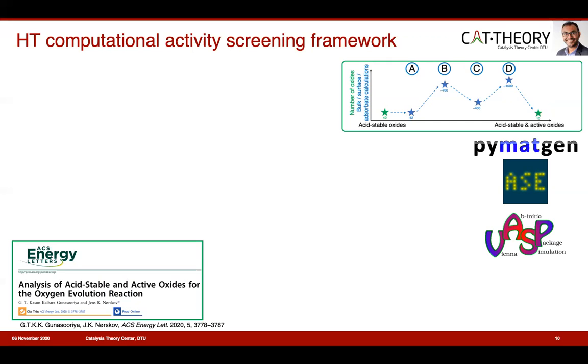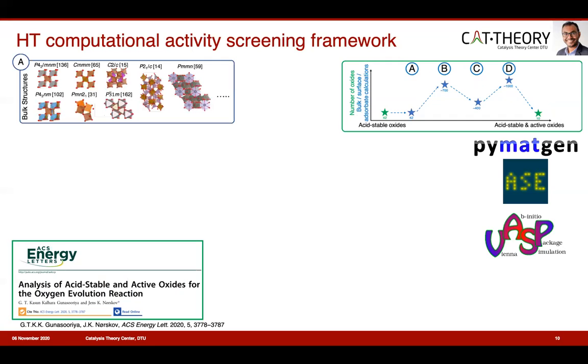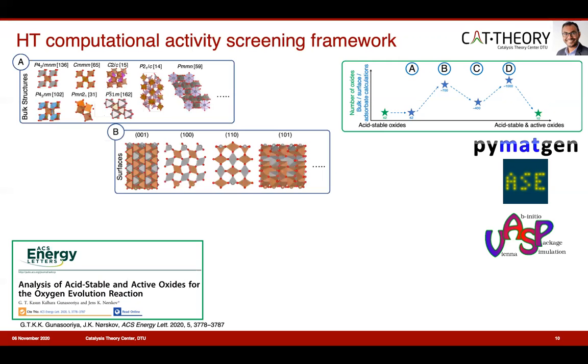In this work, we overcame the aforementioned challenges for high throughput catalyst screening by developing a workflow that systematically investigates the OER activity of acid-stable oxides. In the first step, we optimized the bulk structure and then generated the surface models that fulfill stoichiometry from their respective optimized bulk structures. Surface generation was only considered up to a maximum Miller index of 1. For a given facet, there are multiple surfaces with different oxygen atom terminations. So to determine the most stable surface for a given material, we considered all of these surfaces and calculated their corresponding surface energies, and we use the one with the lowest surface energy for a given facet.